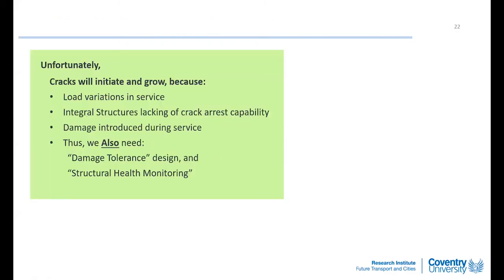The problem with this is that a crack will initiate somehow at the surface, and it will grow because we have load variations in service. We should also expect accidental damage like scratch marks or impact damage. So integral structure has a problem: the lack of crack arrest capability because they don't have redundant members of structure. So damage introduced during service has to be tolerated. Therefore, we also need a damage tolerance design concept, and we also need structural health monitoring.